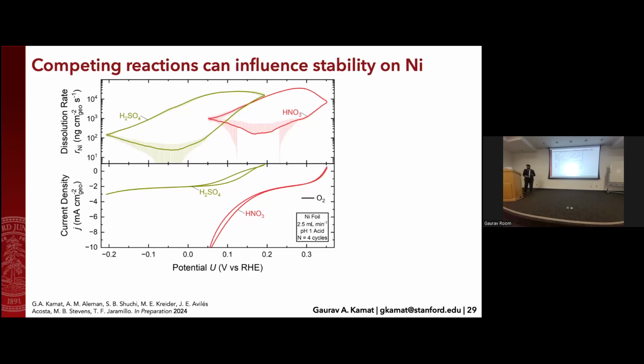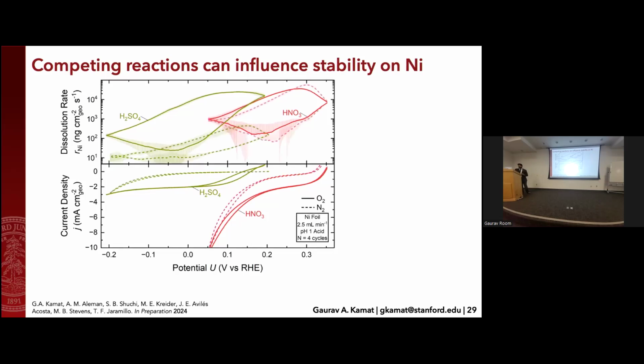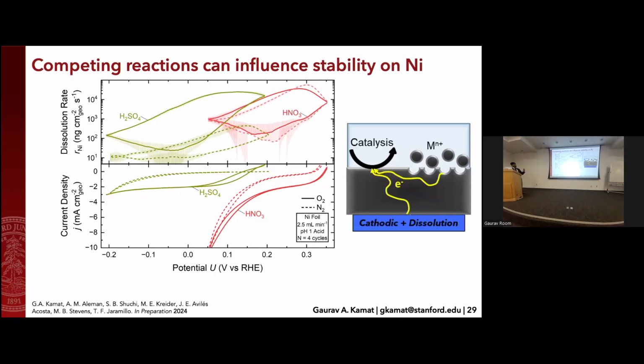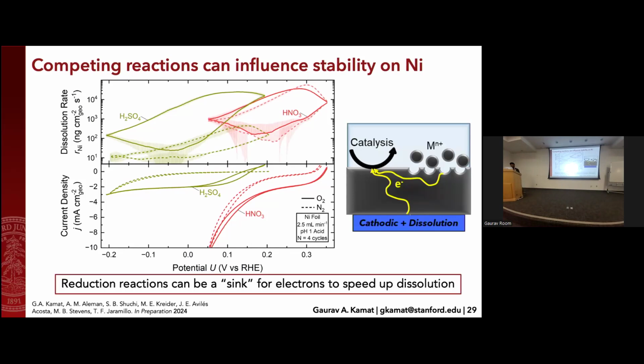The issue is we have to also do this under nitrogen to make sure that we're actually confirming oxygen reduction is happening. So if I do this under nitrogen, you actually still see the same current density trend here, but that current density has now flattened out for sulfuric acid. And that's because you actually have a competing reaction. You have nitrate reduction that is happening on your nickel surface when nitric acid is present.